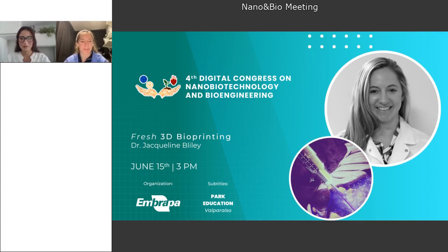So I think I am understanding what this question is asking. When we're printing, we're actually printing layer by layer. So presumably if you have an accurate layer deposition, you should be moving above that layer and printing onto the next layer. We really don't have any issues with dragging of our printed material. Part of that is we're depositing a fluid material and it's gelling in the bath. Then it moves up one layer and starts depositing on the next layer, so we avoid running into other layers when we're printing.